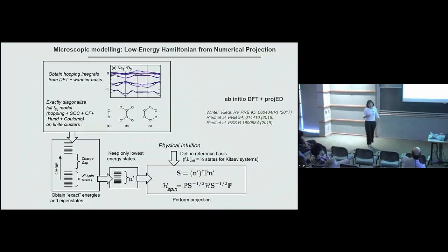So now, what we did in recent years is to develop a method from ab initio that allows us to extract these exchange interactions for these materials. The method is basically we perform density functional theory calculations, so electronic structure calculations. From these electronic structures, you can extract the hopping parameters, so the tight binding parameters, by doing linearization, as well as the Coulomb and Hund's coupling interactions by doing constrained RPA. And then one obtains multi-orbital relativistic models that we exactly solve with exact diagonalization on finite systems. So one obtains exact eigenenergies and eigenstates.